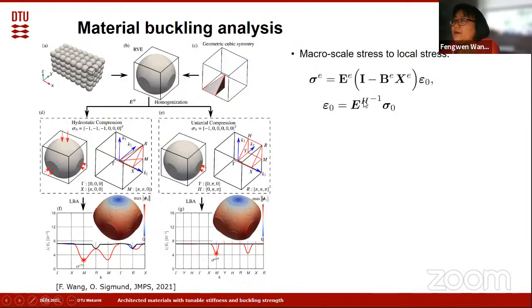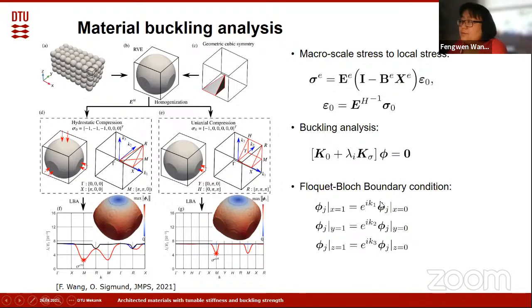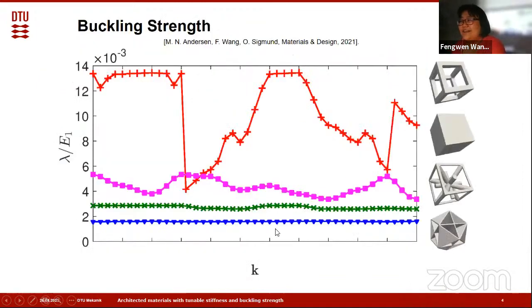To summarize, first we convert the macro scale stress to a local stress, use homogenized material properties, then we perform linear buckling analysis in order to capture all the possible buckling modes. Then the material buckling strength is determined by the lowest possible critical buckling factors. We use this for material strength evaluations. We studied four different microstructures. This plot shows the corresponding band structure, the first band structures. We can see, compared to the stiffness optimal closed wall microstructures, open wall cells outperform in terms of buckling strength.